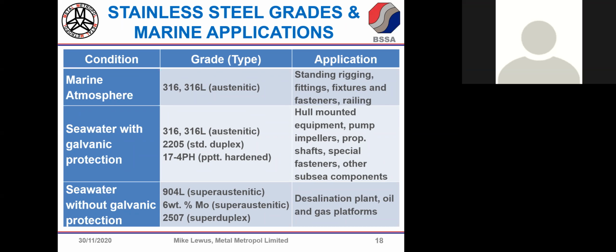316. Well, to put it in perspective, I didn't draw attention to the chloride in seawater earlier on the slide, but there's pretty much 3.5 grams of sodium chloride in every litre of seawater, which means the ppm is 35,000 ppm chloride typically in seawater. And 316 would only be recommended normally in environments that have got not more than about 1,000 ppm chloride. So immediately you know you're testing the material if you're just immersing it in seawater, hence the need for galvanic protection, but not just on 316, on a significantly more corrosion resistant material like 2205, which is referred to as standard duplex and used in prop shafts, for example, that would need protecting too.